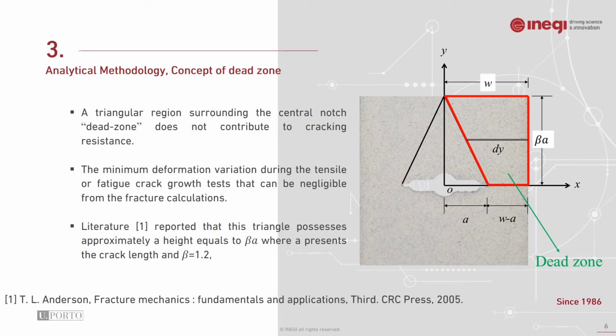In this slide, I'm going to give some description on the analytical methodology based on the stress dead zone concept. So on the right side, you can see an image which is showing the plate with the central notch, which is pre-cracked. The region which is highlighted in red is demonstrated as the dead zone, which means that this is the minimum deformation variation during the tensile test or fatigue crack growth test that can be negligible from the fracture calculation. So the literature, Anderson, as you can see on the bottom side, reported that this triangular region possesses approximately a height equal to beta times the crack length, where a presents the crack length and beta is 1.2.